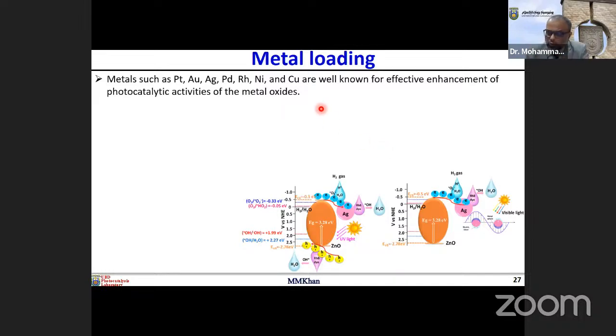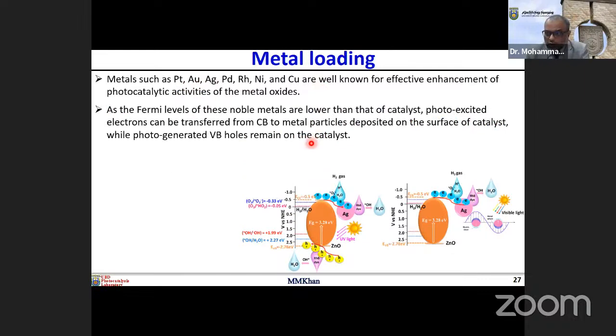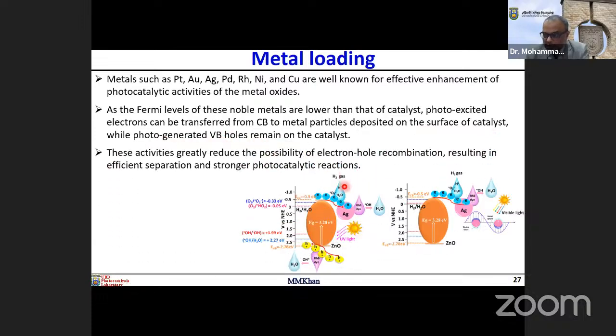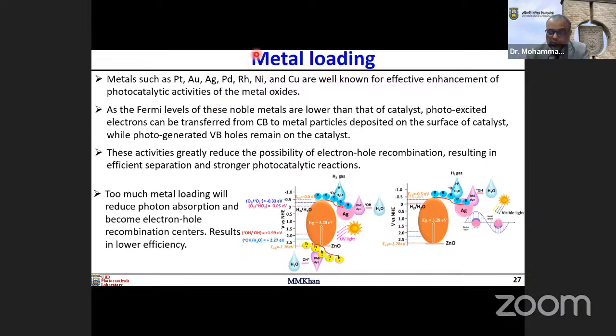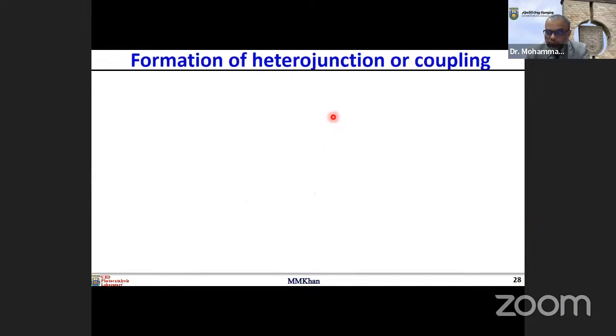So we can modify the photocatalyst using different metals. It depends on your application and all. So doing that, as the Fermi level of these noble metals is lower than that of the catalyst, photoexcited electrons can be transferred from CB to metal particles deposited on the surface of the catalyst, while photogenerated VB holes remain at the catalyst here. So this is the mechanism here. So this is another strategy that we can do, by metal loading.